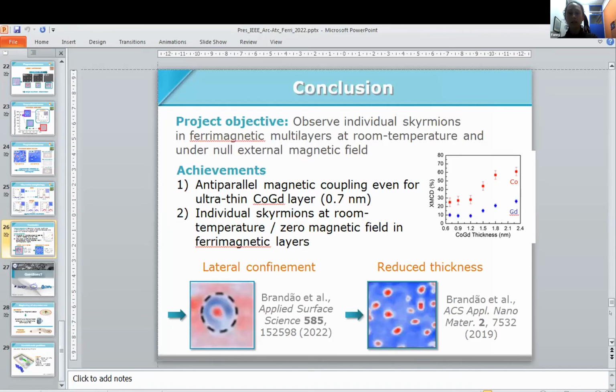And in the two strategies that we used, either to have a lateral confinement or reduced thickness of the ferrimagnetic layer, we were able to stabilize some individual skyrmions.